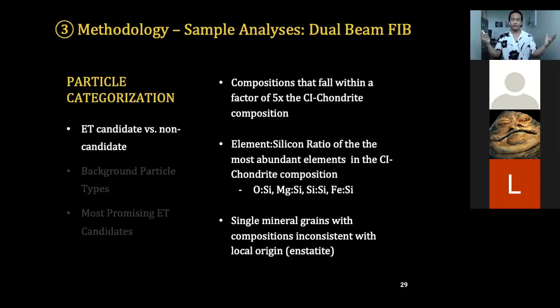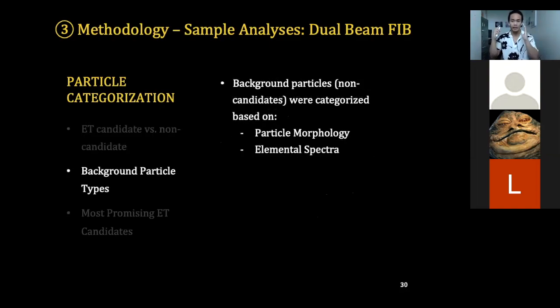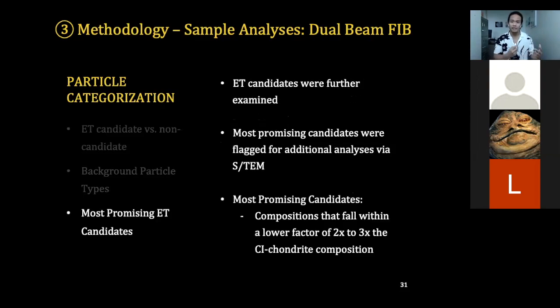After we separated those into two categories, we then look at the bulk background particle types and categorize them even further by looking at their particle morphology and elemental spectra. Once we've done that, we go back to our extraterrestrial candidates and examine them further. These most promising candidates have compositions that fall within an even lower and stricter factor of 2 times to 3 times the CI chondrite composition.